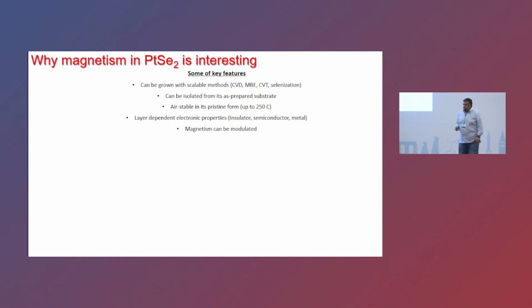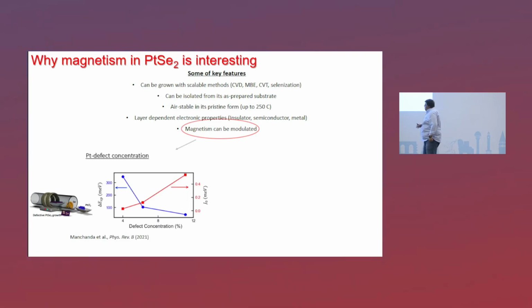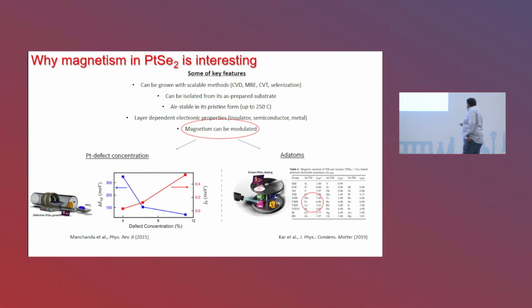I'm a material scientist, and we are very interested in manipulating materials. One of the things we are quite interested in nowadays is modulating this kind of magnetism at the ultra-thin limit. There are lots of predictions that by tuning or modulating the defect concentration of the platinum atoms in this material, we can increase this relatively low Curie temperature of 13 Kelvin up to room temperature. Or we have another approach motivated by some calculations: if you can dope your material with transition metal atoms, you can again increase the Curie temperature.